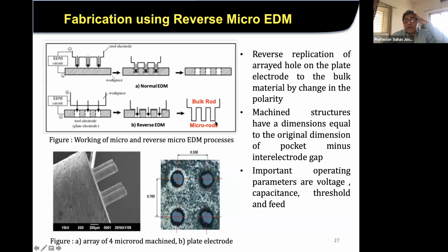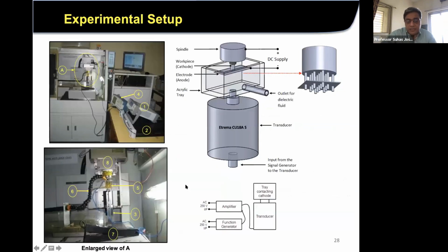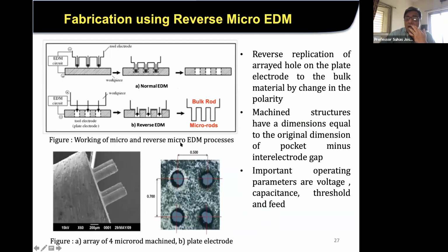So going in that particular direction, we have developed another process which is called reverse micro-EDM. So what is done here is that we know that in the EDM process, we actually use the electrodes and we make the holes on the surfaces. But in reverse EDM, what we do is that we take a plain workpiece, we take an electrode which has holes, and we try to penetrate the workpiece inside the electrode. So you can get these kinds of projections on this.